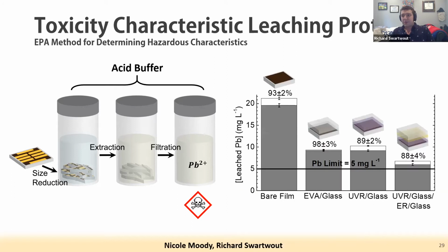If it's above a regulated limit, it's toxic, with implications for EPA regulation. If you do this test with multiple perovskite encapsulation methods, the bare film unsurprisingly leaches much higher than the EPA regulated limit of 5 milligrams per liter. But a standard physical glass encapsulation, a glass UV epoxy encapsulation, and even a triple glass encapsulation method touted in a prominent journal as a way to contain lead, all do not pass this TCLP test.